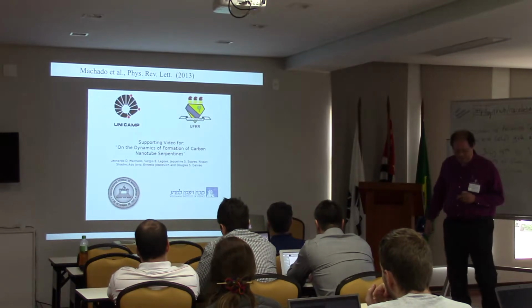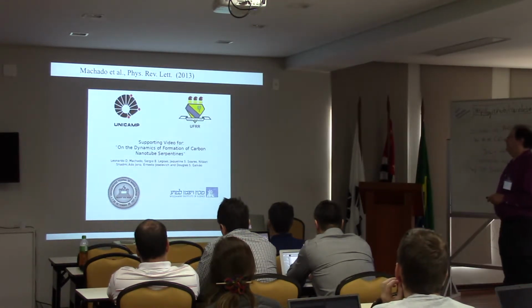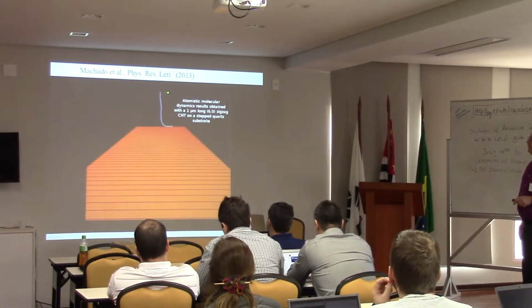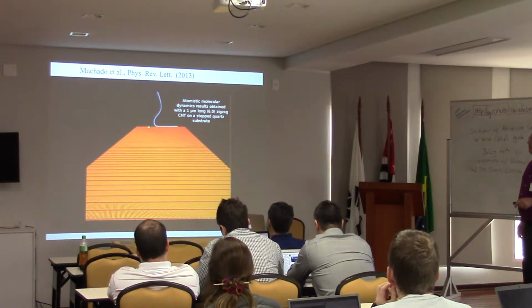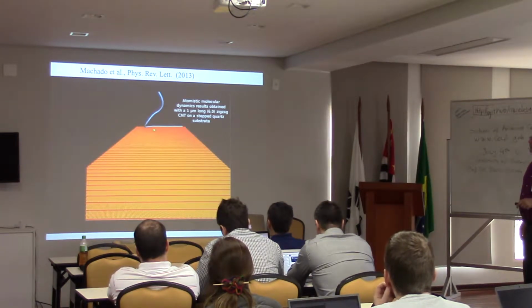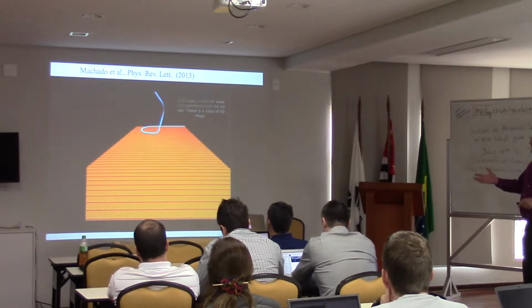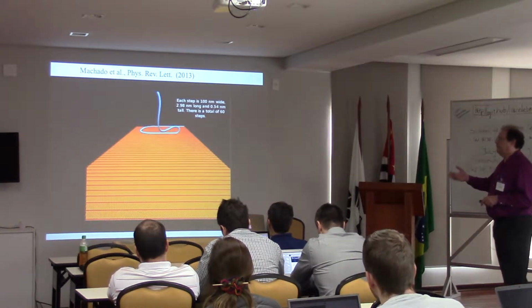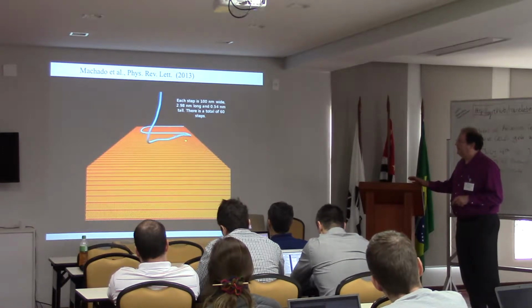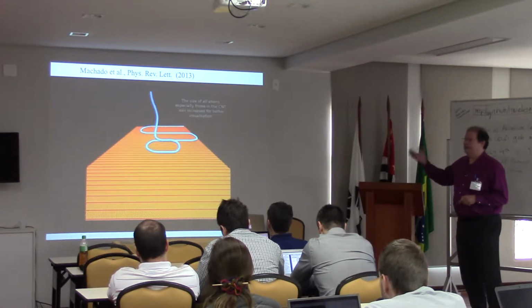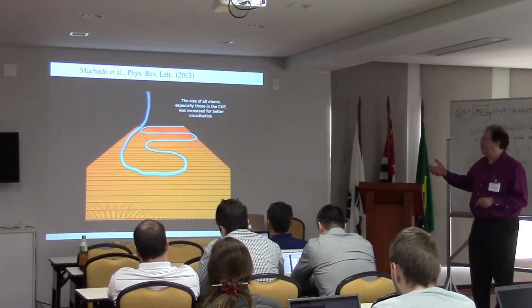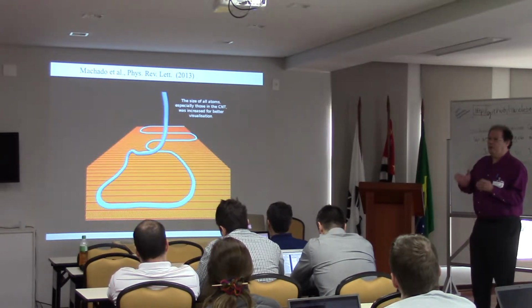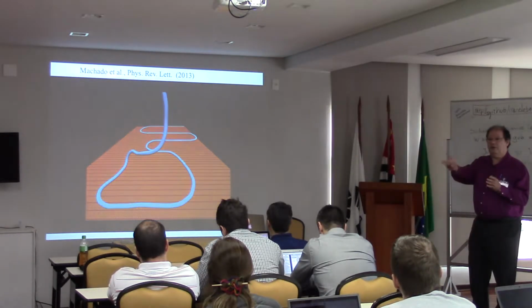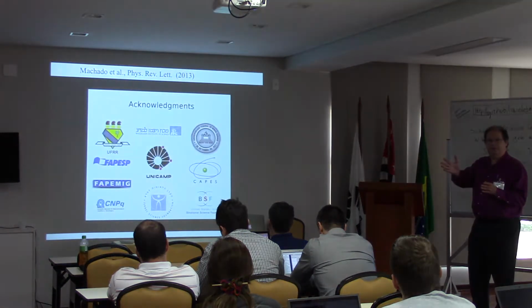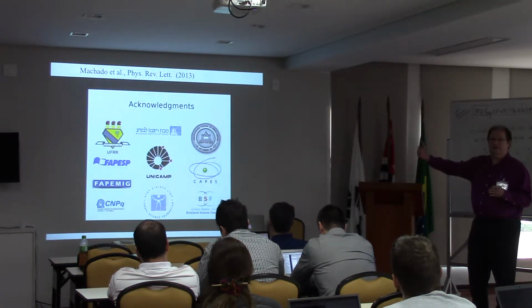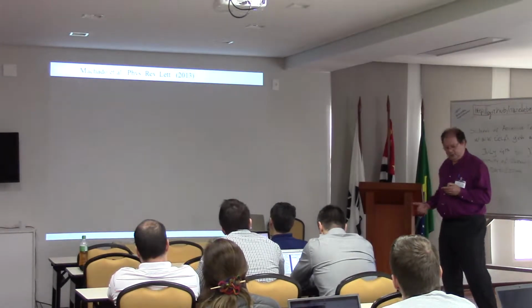Let's show the movie. The movie provides a better idea how it forms. It interacts with the substrate, it pulls the tube down, it slides a little, but this is silicon oxide substrate, the same that was used in the experiment. It's a sticky substrate. It stops the sliding until the limit of the elasticity and the kinetic contribution, then it forms. You can control the separation just by increasing the flux of the gas in the experiment. In the simulation, just increase the applied initial velocities.